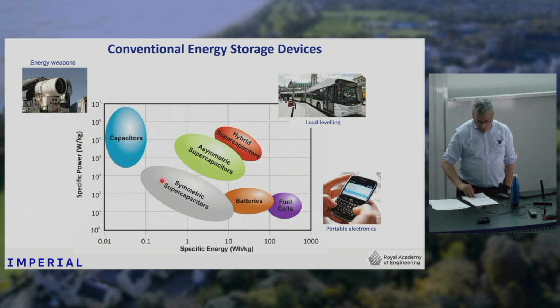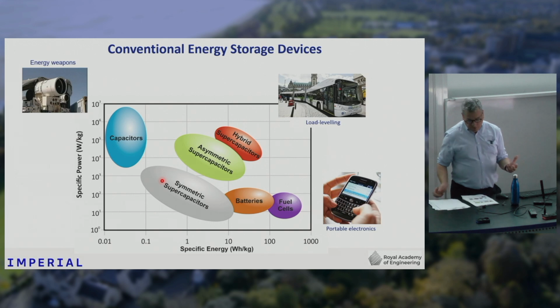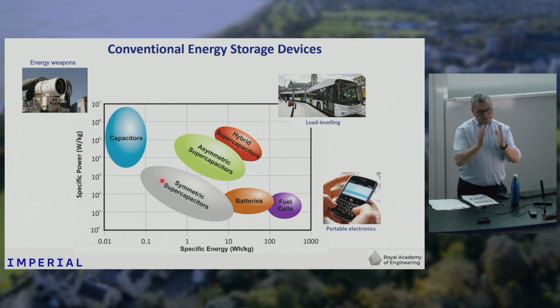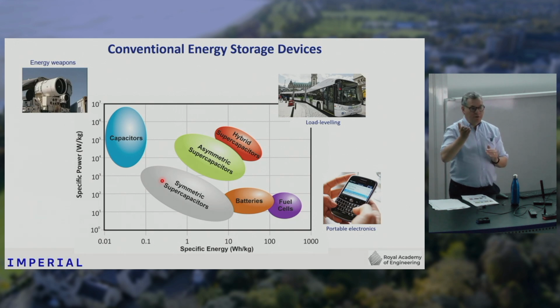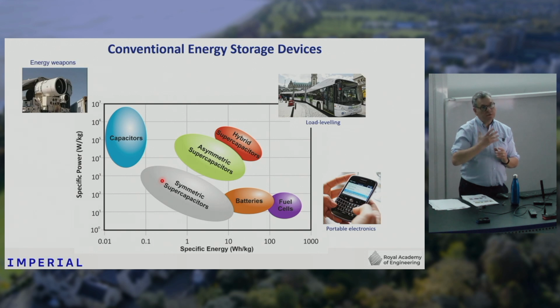So supercapacitors are essentially a type of capacitor. You might remember from school, the way a capacitor works is you have 2 plates which are a certain distance apart, and the closer you get them together, the higher the capacitance, and the amount of charge you can store is related to the surface area of those plates. So in the supercapacitor, we make that surface area really, really large by making the surface really tortuous. So it's very high surface area. And then the charges are actually stored at the interface between the electrodes and the electrolyte, so rather than being millimeters apart, they're on the order of nanometers apart. By doing that, you can develop supercapacitors which can store considerably more energy than a conventional electrostatic capacitor.